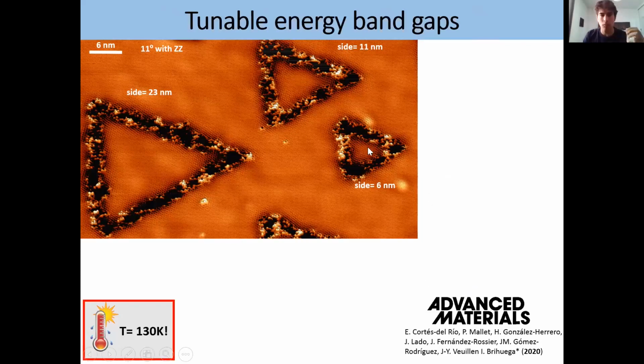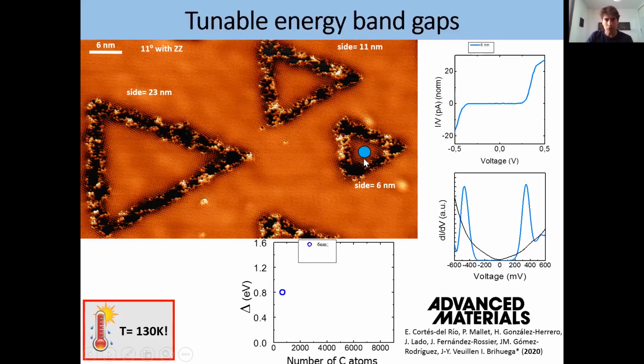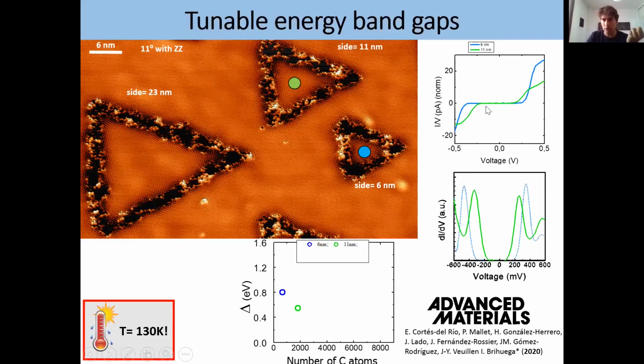Here I show you one, which is the same triangular graphene quantum dot, but with different sizes. And of course, if we measure the conductance here, we see the opening of a very clear gap, okay? And here we see the distance between the two peaks. If we now go to a larger structure, we should see that the gap gets smaller, and that's what we see. Still a very well-defined gap, but it's smaller now. And if we go to an even larger structure, then again a gap, but it gets smaller and smaller.